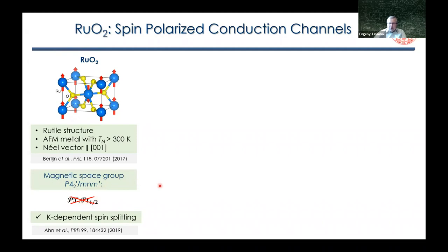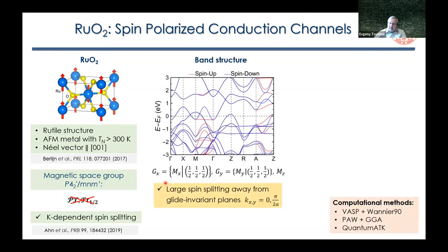So as a result, we should expect k-dependent spin splitting and spin-dependent, momentum-dependent Fermi surfaces. And this is indeed confirmed from electronic band structure calculations, whose results are shown here. This is the band structure for spin up and spin down electrons, shown in red and blue, along high symmetry lines in the Brillouin zone.